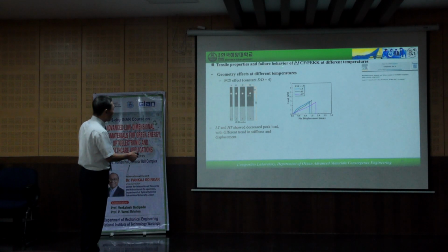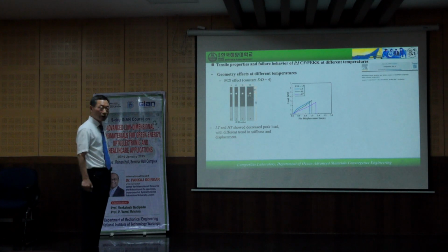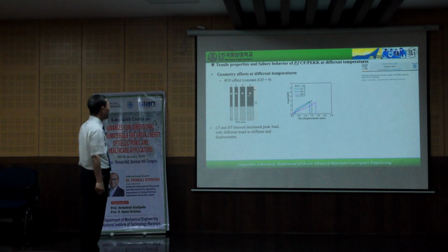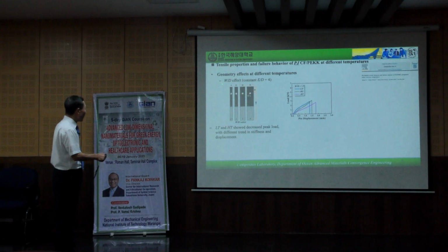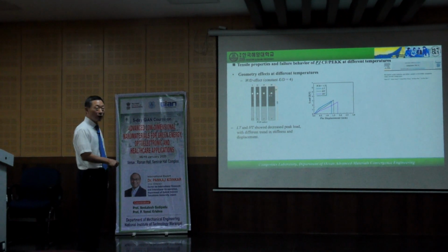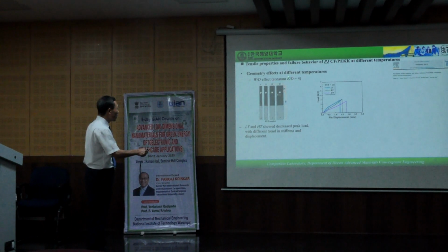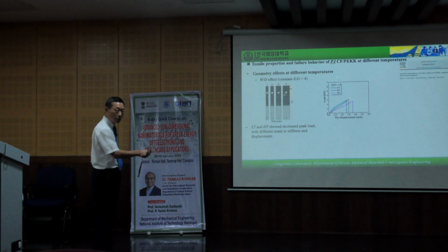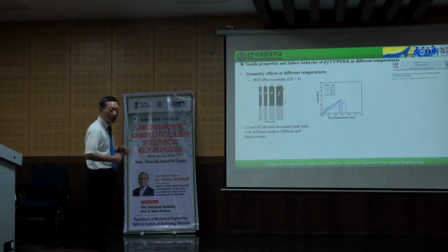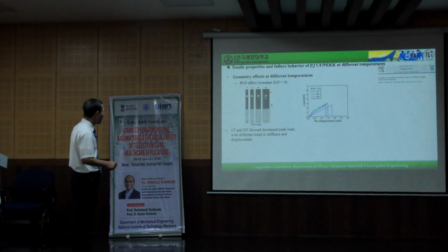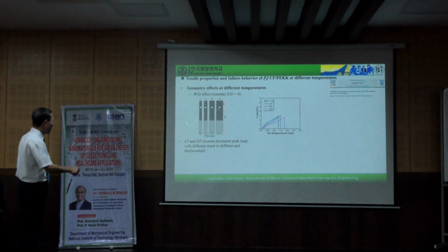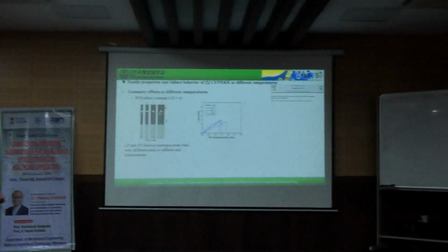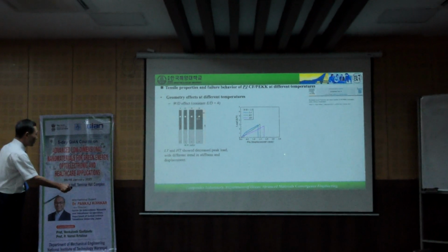The failure behavior of pinned joint at different temperatures, W/D effect under constant E/D ratio equal 4. Just compare the result. We prepared this kind of specimen. The result is like this.